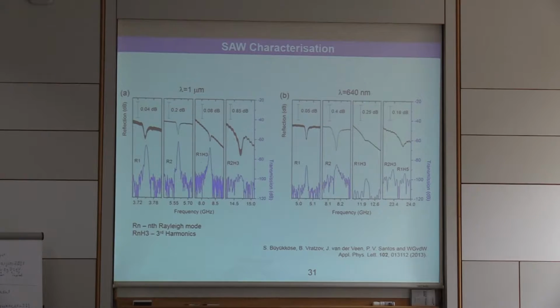The experiments were, again, the S parameters, the transmission and reflection data. This is for lambda is 1 micron, so that would be a double finger design with a feature size of 125 nanometer. So there you have to double the wavelength. Also here you can see Rayleigh modes. This is the fundamental, this is the second mode, but also what you see is harmonics, third and even fifth harmonics of Rayleigh modes. So these are the more conventional harmonics, but then of the different modes.